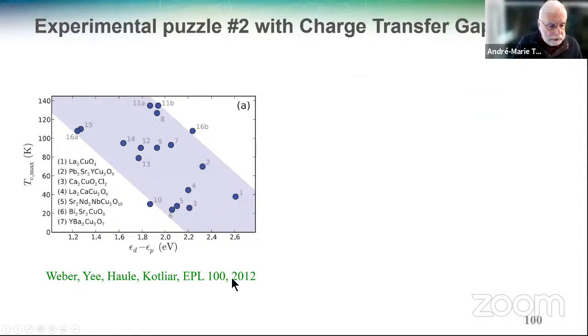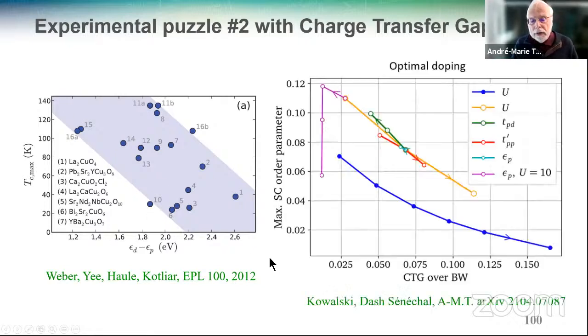So there was this paper by Weber. I'm almost done, so thank you for your patience. Weber, Yee, Haule, Kotliar. They showed here the TC as a function of epsilon D minus epsilon P. So that's not the charge transfer gap. It's a microscopic parameter. And there are many microscopic parameters that you need to fit to have a given charge transfer gap. But nevertheless, you see there's this anti-correlation, that TC goes down when the charge transfer gap increases.